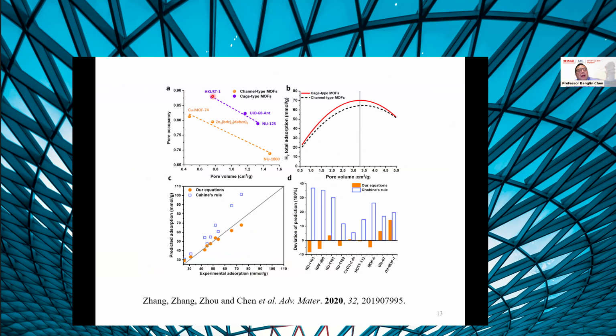So the hydrogen occupancy, meaning the degree to the saturated hydrogen, supposed to be 100%, will be higher than those MOF material with linear channel. And we realize that this empirical formula is much better than the original empirical formula with linear relationship. So once we know the porosity, pore volume, we are able to estimate their performance for hydrogen storage. And you will see that traditional MOF have this maximum storage capacity.